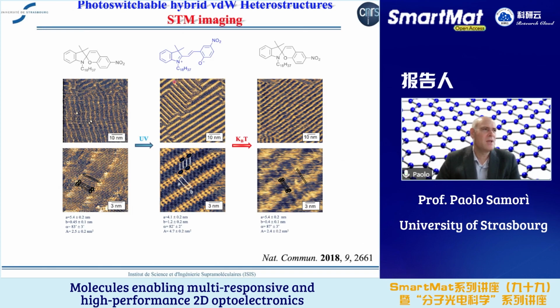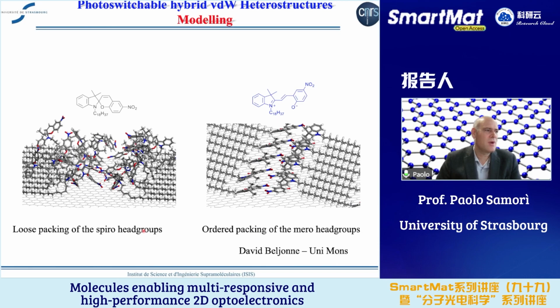If you look at a smaller scale, you can do scanning tunneling microscopy images, and then you can see that the spiro molecules form lamellar structures, and on the very small scale on the bottom, you can determine the unit cell of this lamellar structure. You can irradiate with UV light, and you trigger the isomerization from the spiro to the mero, and in this case, we can see that another type of lamella packing is obtained. You can see that the unit cell of the spiro is different from the one of the mero. And then if you wait some time or you irradiate with visible light, the adsorbed molecules undergo back isomerization to the spiro, and you can see this is observed by the same unit cell that you have here compared to the first column.